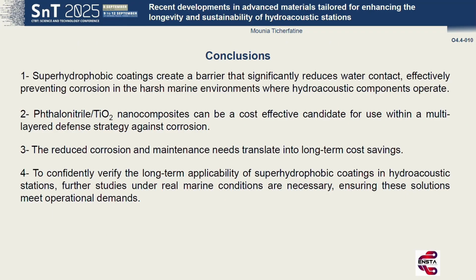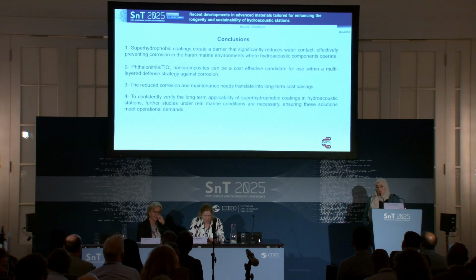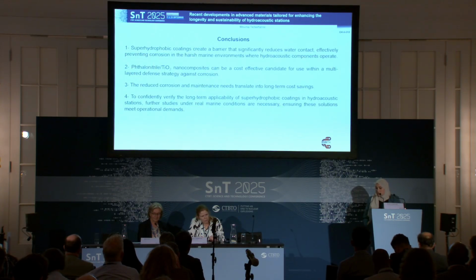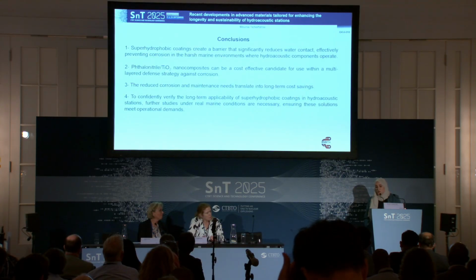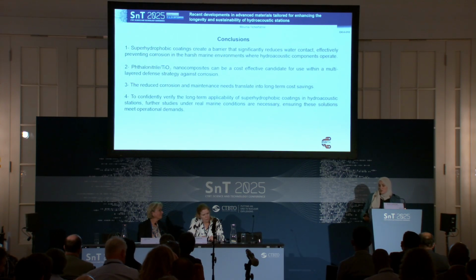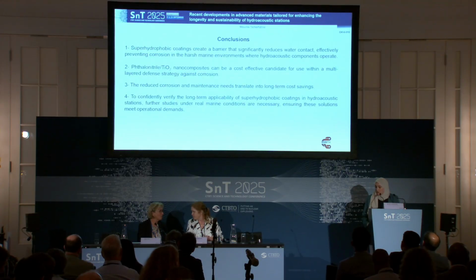degrees Celsius. So as a conclusion, our superhydrophobic coatings create a barrier that significantly reduces water contact. And in order to prevent corrosion in these harsh marine environments where we have our hydroacoustic components, phthalonitrile/TiO2 nanocomposites can be a cost-effective candidate for use within a multi-layered defense strategy against corrosion. Also, the reduced corrosion and maintenance needs translate into long-term cost savings. To verify the long-term applicability of the superhydrophobic coating in hydroacoustic stations, it should be further studied under real marine conditions if necessary, ensuring the solution meets operational demands.